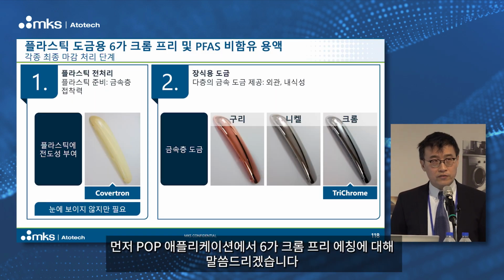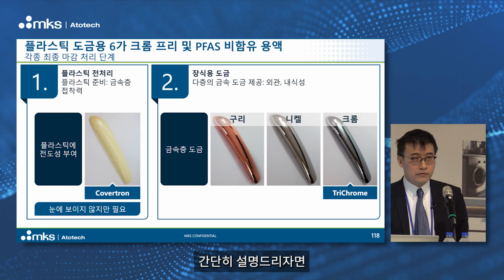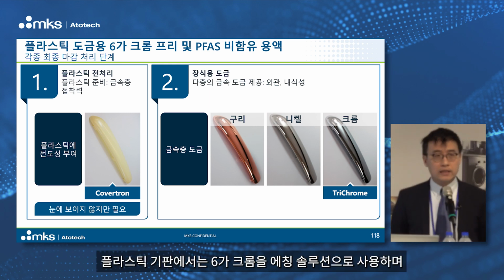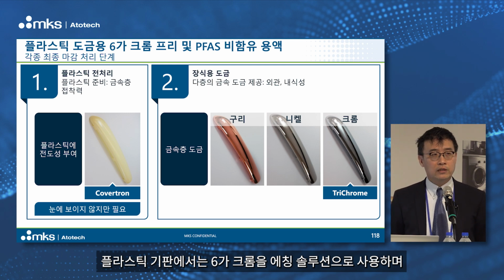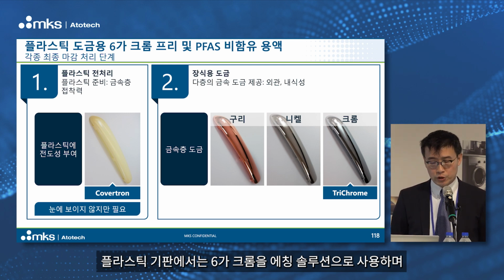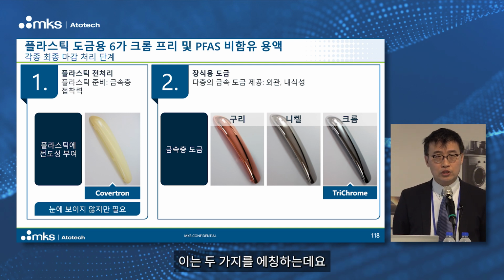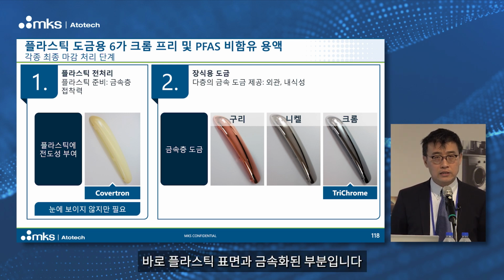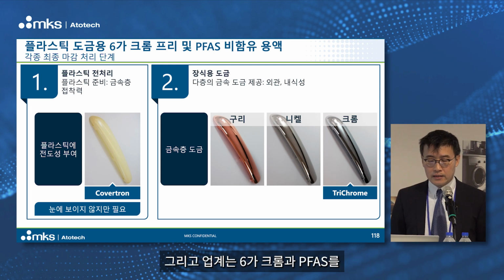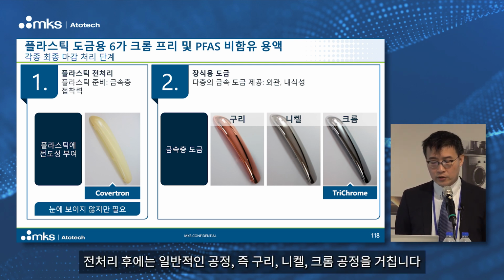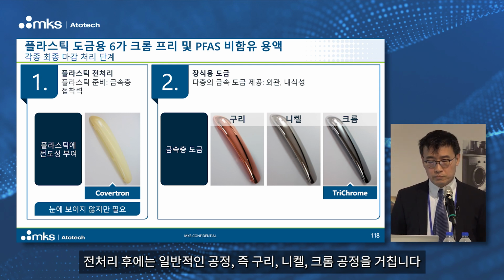First, let me start with the Chrome 6 free etch for POP application. A very short introduction: everyone knows that on plastic substrate, we use chromium trioxide as an etching solution. It etches the plastic surface and metallizes the parts. We are using chromium 6 and also a PFAS film suppressant in this application. After the pretreatment, we go through the normal process like copper, nickel, chrome.